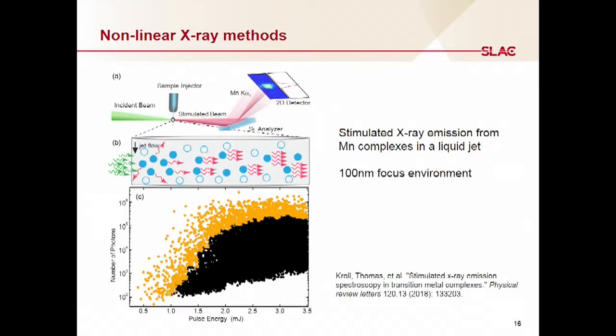This was an experiment that really can only be done at CXI in the 100 nanometer focus, where these people did stimulated X-ray emission from manganese complexes in a liquid jet. What this means is that stimulated emission, you could probably think that's actually a laser term, which it is. Because of the very high power density, they were able to see a kind of population inversion. You have this very intense laser beam coming in, and typically this causes stimulated emission. But because of the very high power, you get more excited states than ground states. As this particle gets excited, it emits photons, which in turn amplify as it continues along in this jet.